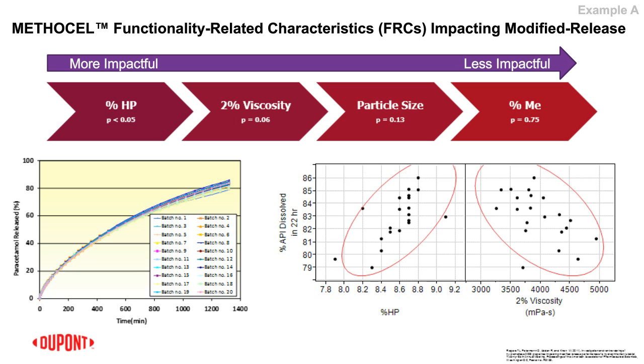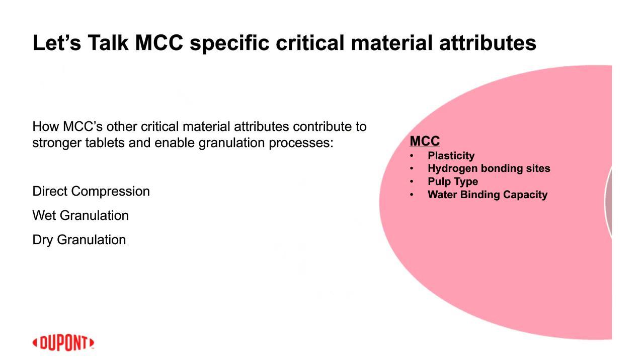And so I'll go back to the fact that these 20 batches did deliver very reproducible modified release performance. But if you really dig into the data, you can see that there are relationships there, statistically significant relationships. So this is actually very interesting. It's a very robust, consistent product, but also you have some parameters you can fine tune to further control the performance of the polymer and the final formulation.